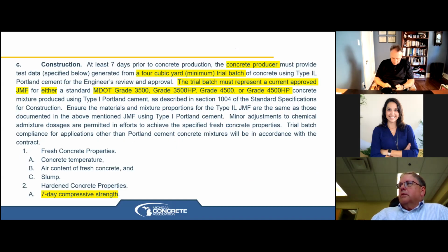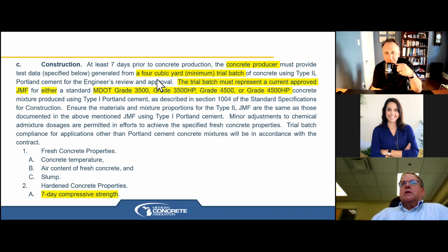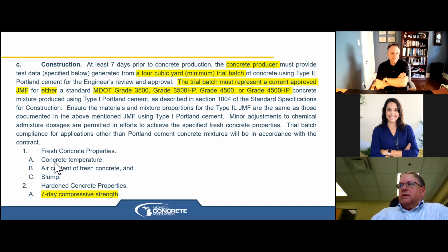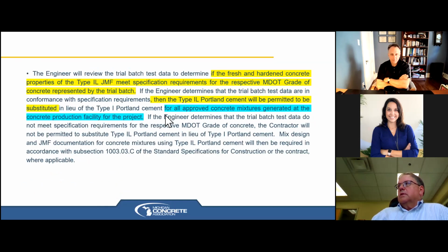It does require that the concrete producer produce a 4-yard minimum trial batch of one mix that they've been using. We wanted the producers to actually have some experience with this product before it goes out on the street. They needed to test the fresh properties with a 7-day break. But once they did it for one mix, then that plant is good for all of the approved concrete mixtures produced at the concrete production facility for the project. So once they do one trial batch, they're good for making that 1-for-1 switch on all of their materials.